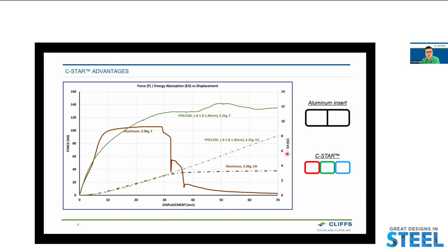And for the energy absorption, from 0 to 33 millimeter, these two dashed lines are tangled with each other. And after 33 millimeter, where the crack in aluminum propagates across the section, the energy absorption line goes flat. However, our C-STAR still builds up energy very quickly. So in conclusion, from 0 to 33, we are close, and C-STAR is very competitive to the aluminum baseline. And after 33, C-STAR outperforms aluminum.